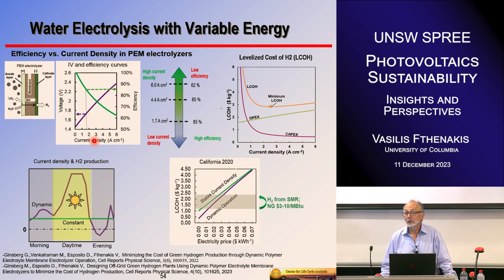Higher current density means more electrons and more hydrogen coming out, but at a penalty of efficiency. So the efficiency can be reduced. If, for example, you get to 6 amperes per square centimeter, the efficiency will be only 62%, down from 85%. But you get more hydrogen.